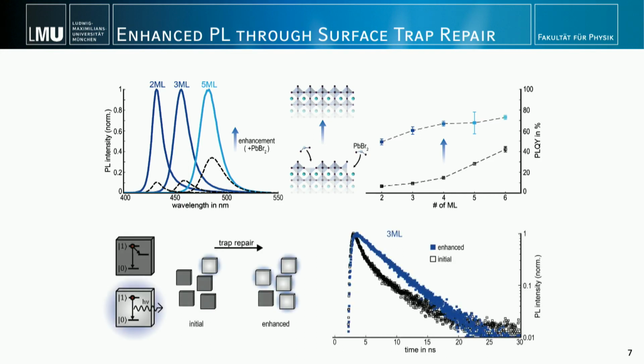So let's take a look at this model. Whenever we measure a spectrum, we don't do it for a single crystal, we actually measure thousands of crystals at the same time. So you would always measure some crystals which have a high efficiency, some have a lower one, and as indicated here at the beginning, before we do this repair process, we have probably many dark gray platelets which contain defects, thus they are not very efficient in their emission properties. After the repair, we have mostly a dominant contribution of enhanced bright platelets, which mainly do recombination via sending out a photon, and this could also be confirmed by looking at time-resolved spectroscopy, where the decay curves become more mono-exponential.